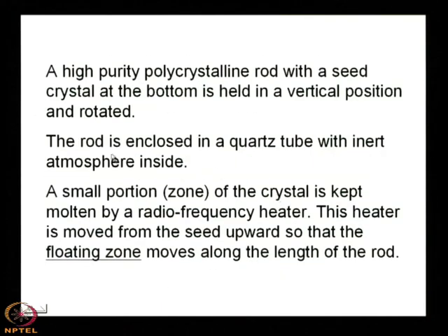Now, the rod is enclosed in a quartz tube with inert atmosphere inside. It is as usual. There also in the Czochralski technique, it is covered with a quartz tube, and argon is passed through the quartz tube. Why was the argon necessary for the crystal growth? Yes, to replace basically oxygen, etcetera, and to control the oxygen which comes from the crucible.